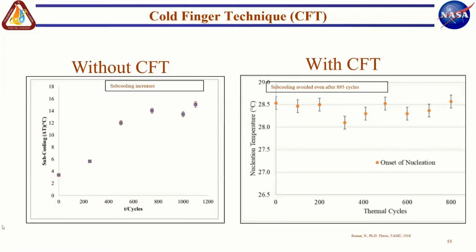And so the graph on the left shows the amount of subcooling you need to solidify a PCM after a certain number of cycles of melting and solidification, where you have done 100% melting and 100% solidification. The graph on the right shows the amount of subcooling that you need after like 800 cycles. If you don't melt the PCM completely, if you just keep about 5% or 10% unmelted, the onset of nucleation requires less than 1 degree subcooling in order to initiate the solidification process. But the enigma there is, how do you predict in an actual power plant when it's going to hit 90% melt?